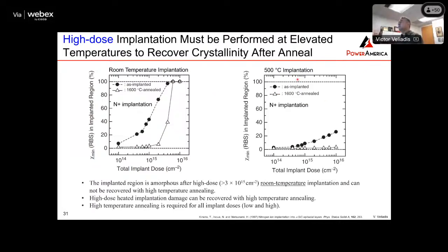And if you do 500 degree implantation, so the implantation is not at room temperature, it's at 500 degrees, you can see that even if you go to high implant dose, if you anneal, you still get a very good surface and you activate the dopant. So once we exceed 3 times 10 to the 15th dose, room temperature implantation does not work anymore. And any damage that happens because of the high dose of the heated implantation, you can recover during the annealing.